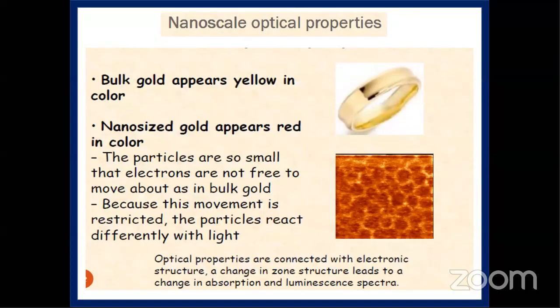And also this is quite interesting. You can see the nanoscale optical properties. The bulk gold appears in yellow color. When you reduce the size to a small scale, you can see the gold appears in red color. The reason is the particles are so small that electrons are not free to move about as in the bulk gold. Because this movement is restricted, the particles react differently with the light.